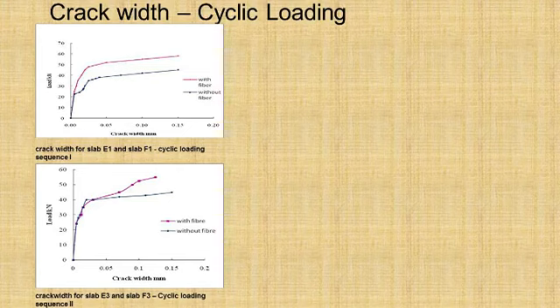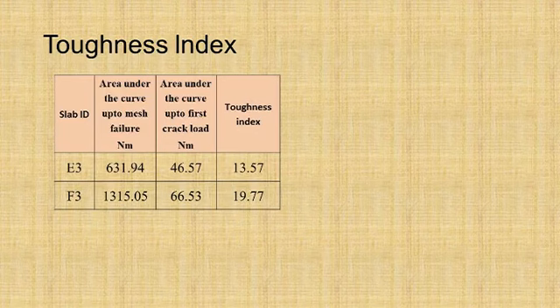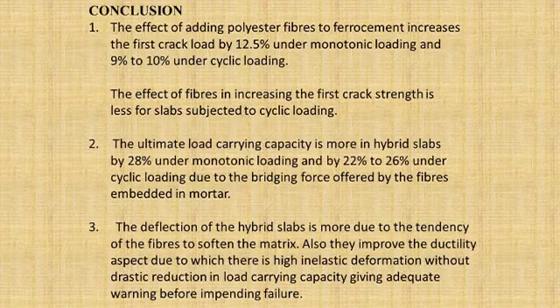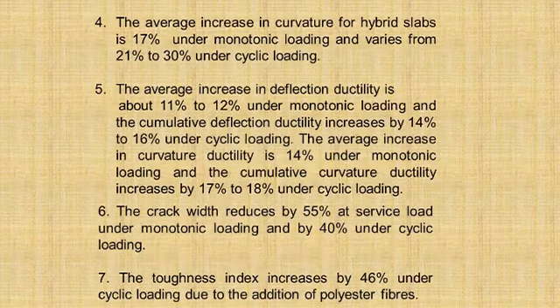So this is for cyclic loading. Everywhere we see that the crack width is less in general for ferrocement hollow slabs, and when fibers were used, the crack width reduces still further. Toughness index was also calculated, and it was found to be higher for slabs with fiber. All these points I've already told in my lecture. Thank you. Now we can have a discussion.